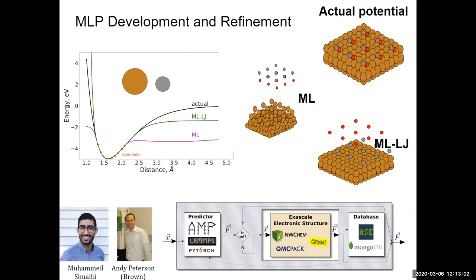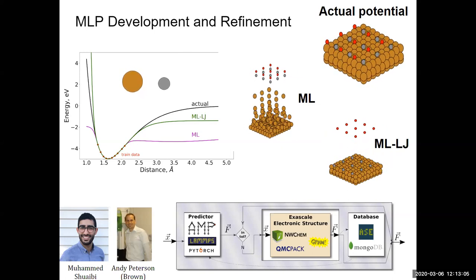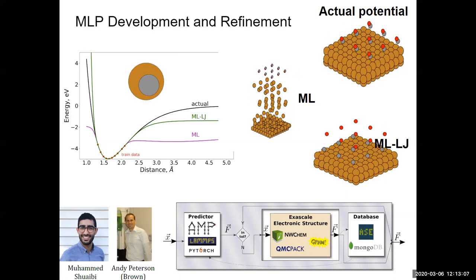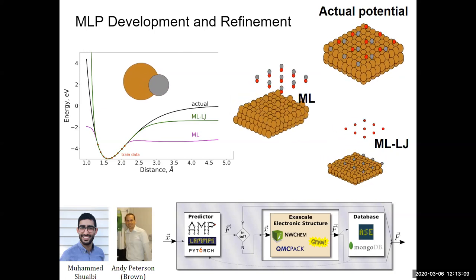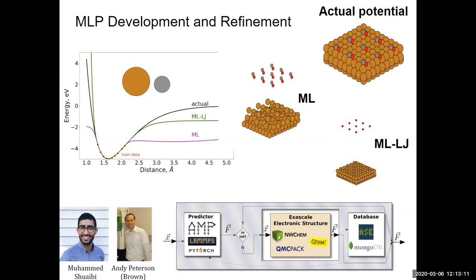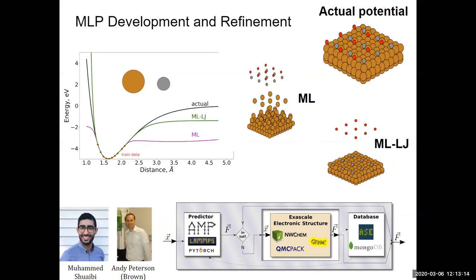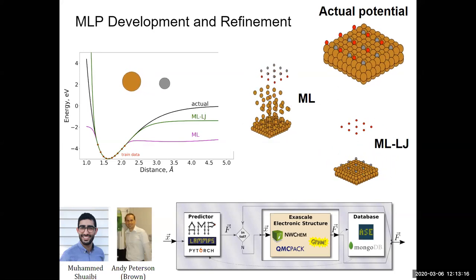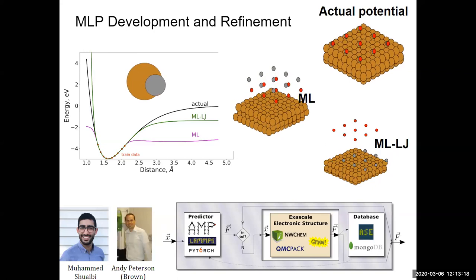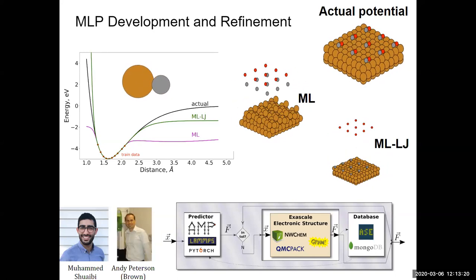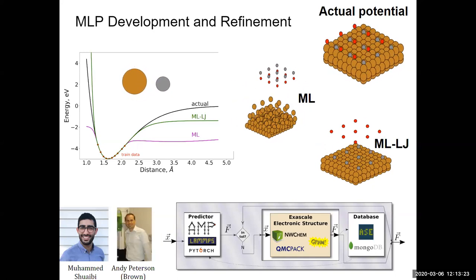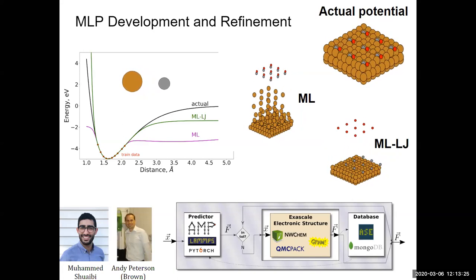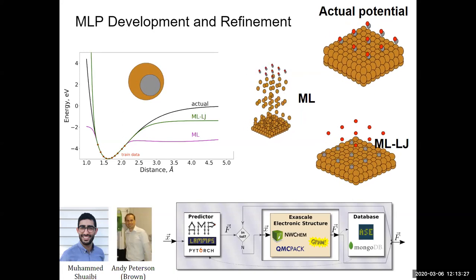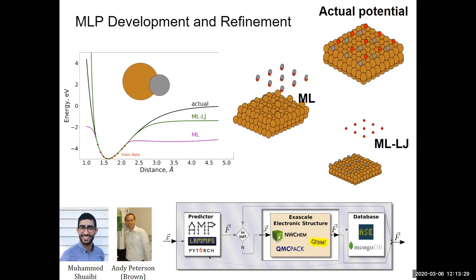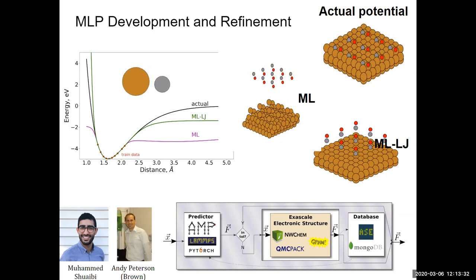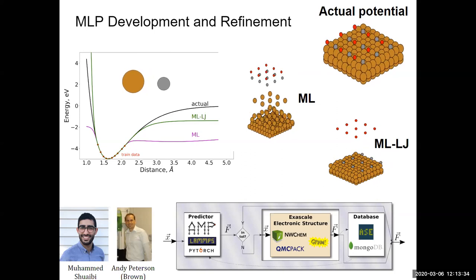And what we found is incorporating just the smallest amount of physics into this, adding a simple classical potential at the very beginning that says, there are some things like van der Waals or Morse potentials, and if you overlap two things, you're going to have a problem. We know the covalent radii, so we don't even have to really fit many of these parameters. Even using that with the same procedure, we get much better convergence. So the CO is still flying off the surface, but the copper looks very reasonable now, and any point from there, I could actually sample and add back to the training data set.